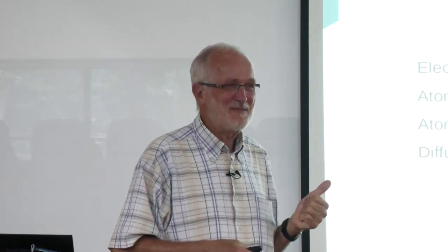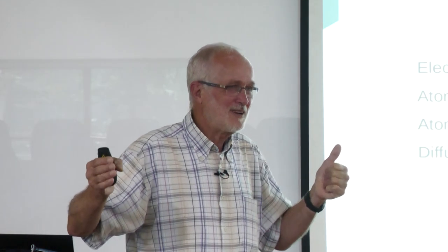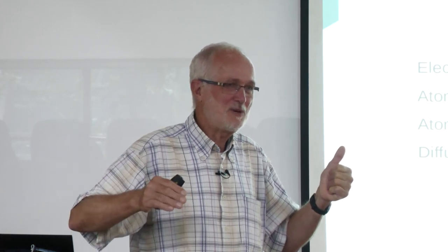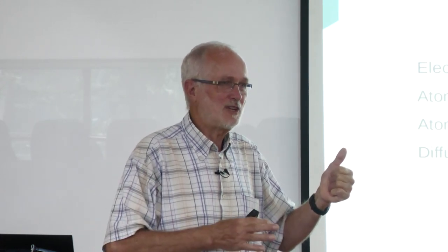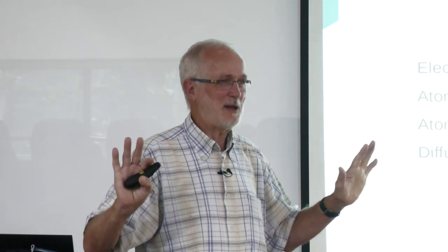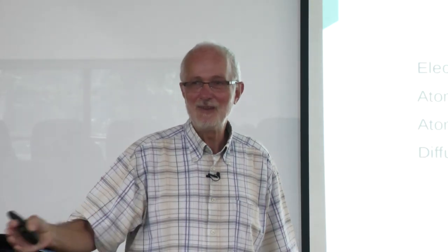Okay, I should not talk too much. In aluminum, there's a strange situation. You all know there is an important class of aluminum alloys, the 2000 series, which contains some copper, and this hardens at room temperature. And if you calculate using the diffusion coefficients, it should not happen, yeah, not even in years. Yeah. And it only happens because you have an excess of vacancies which accelerates the diffusion.